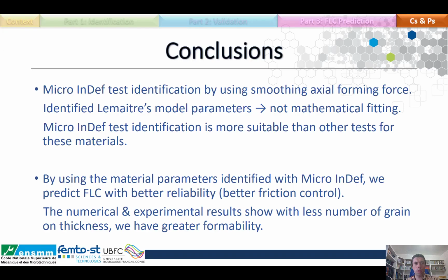So this work demonstrates that micro-indef test identification of the Lemaitre model parameters is not just a mathematical fitting, and that micro-indef test identification is more suitable than other tests for these materials. By using the material parameters identified with micro-indef, we predict the forming limit curve with better reliability due to better friction control. And the numerical and experimental results show that with a smaller number of grains in the thickness, we have greater formability.